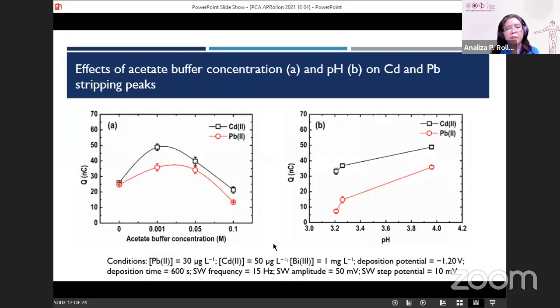And for the effect of the acetate buffer concentration, we can see here that the stripping peak area has a maximum somewhere in this range of concentration of the acetate buffer. For cadmium here, around 0.001, and for lead, it is also between 0.001 and 0.05. So therefore, if we're going to simultaneously determine lead and cadmium, it must be somewhere within the 0.001 concentration of acetate buffer. And the effect of pH is given at the right side.